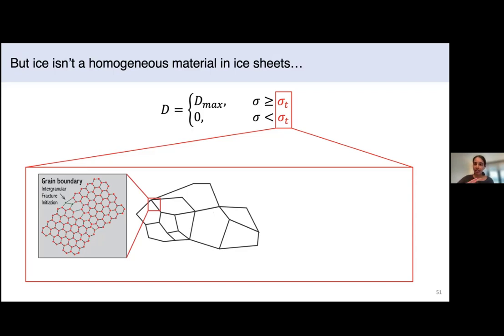If we were to zoom in a lot to the boundary between ice crystals, it would look something like this, where you've got a lattice on one side, which is one crystal or one grain, a lattice on the other side, and what separates them is the fact that they are misaligned. That's what distinguishes one ice crystal from another, the fact that they're at an angle from each other. That means the bonds in between them are quite irregular. Within a lattice, the bonds are very regular, these very strong hexagonal shapes.